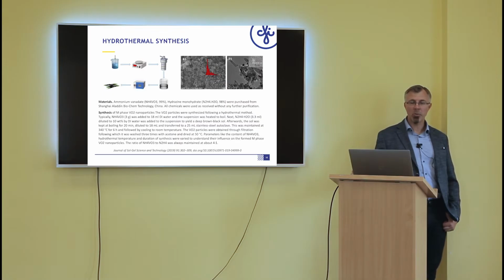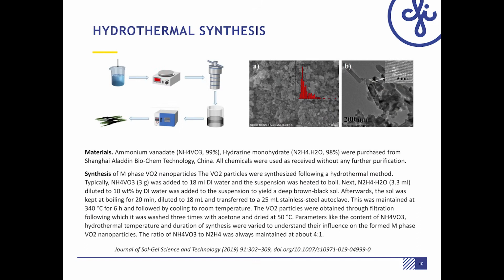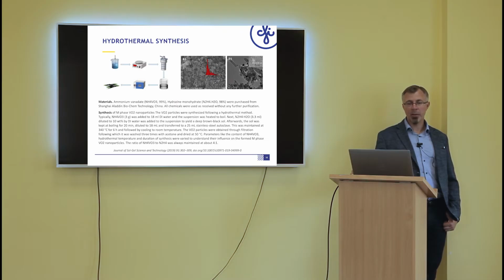Now, in more detail about synthesis of vanadium dioxide nanoparticles. Probably the most popular one is the hydrothermal synthesis method. So we mix precursors, prepare a solution and load it into an autoclave, which we place inside an oven for a certain time and temperature. After synthesis, it is necessary to calcinate the obtained nanomaterials. After that we dry it and obtain vanadium dioxide nanomaterials.